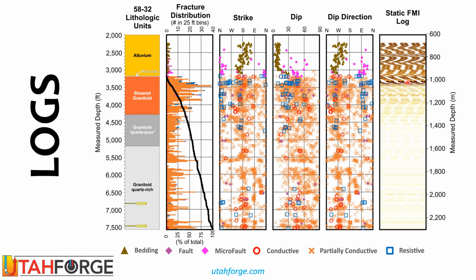Then we get into the sheared top of basement. It's maybe even more conductive, with salty fluid filling fractures. And then as the fractures die out and porosity declines, the rocks get lighter and lighter, less conductive, more resistive with depth. We can also take a look at the fracture distribution. Fractures full of salt water or even the drilling mud are more conductive. We can see that there is a lot of fracturing at the top of the basement next to the abandoned fault surface, and then it diminishes with depth.